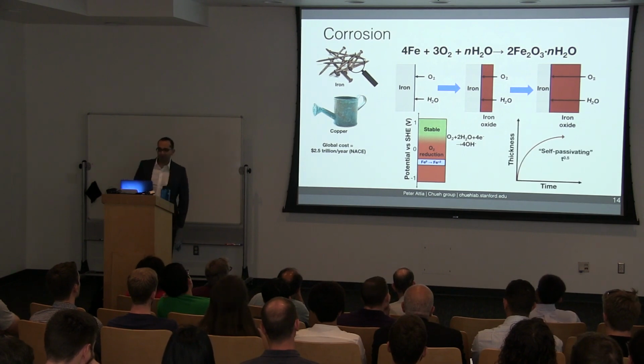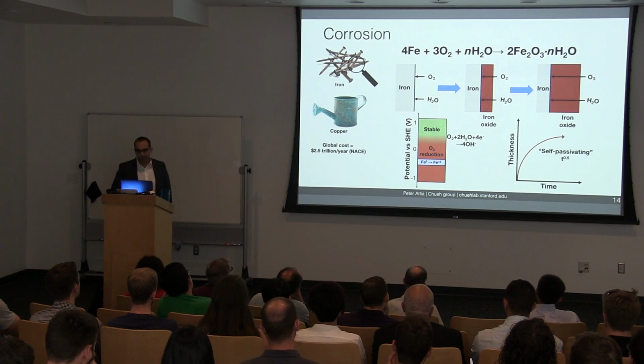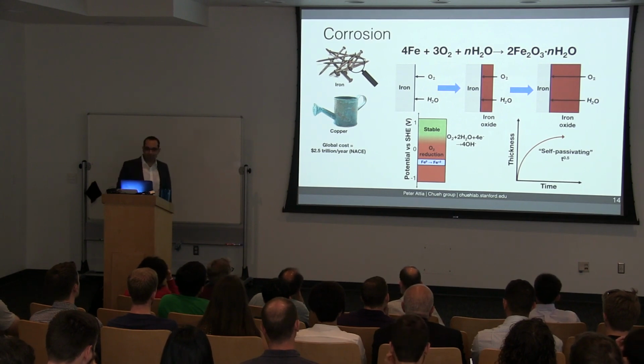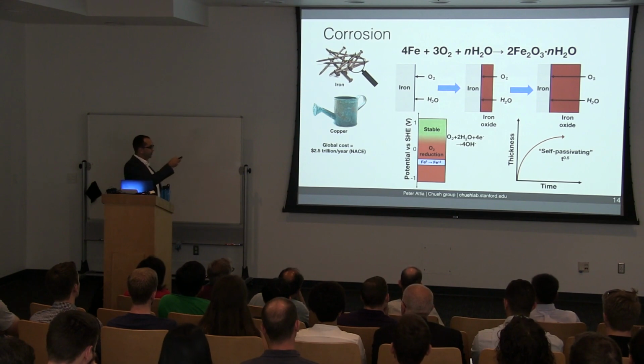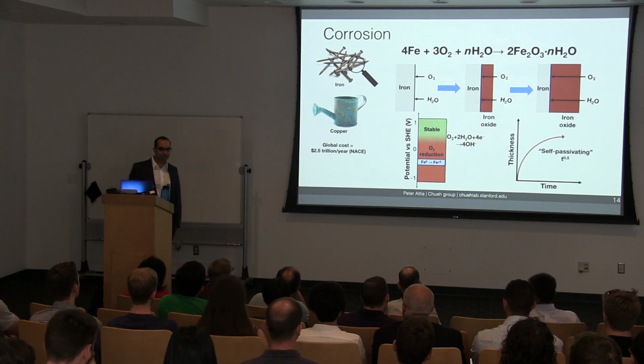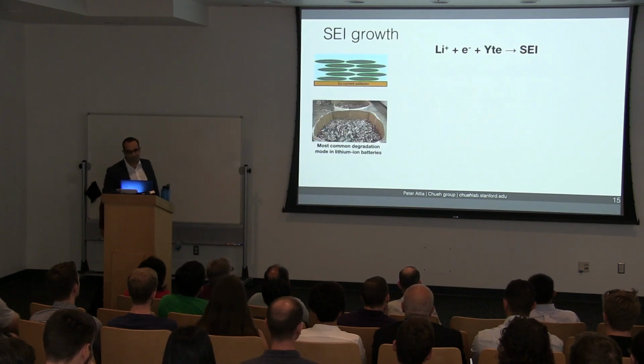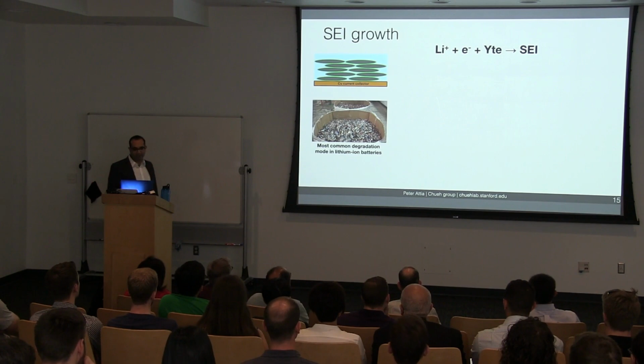What this means is that rust formation is a self-passivating reaction, which means that its growth rate gets slower with time. And as the layer gets thicker and thicker, it takes more and more time for oxygen and water to diffuse through the iron oxide, and thus the growth rate slows down. The general scaling relationship for this is that thickness scales with time to the 1/2. And in general, the fact that we know so much about how rusting works allows us to design ways of stopping it. Now, SEI growth in lithium-ion batteries is actually quite similar to rusting.